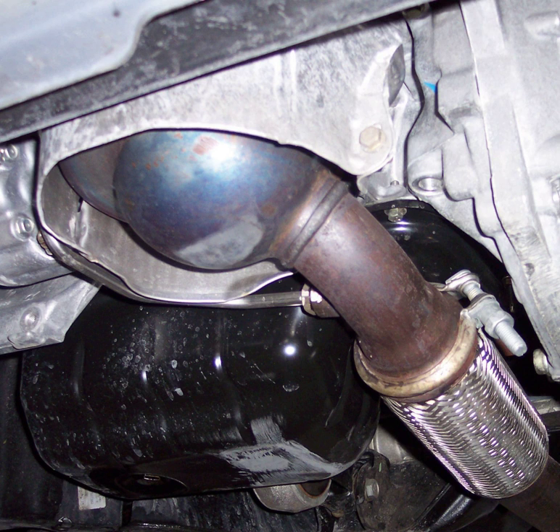The most common filter is made of cordierite, a ceramic material that is also used as catalytic converter supports. Cordierite filters provide excellent filtration efficiency, are relatively inexpensive, and have thermal properties that make packaging and installation in the vehicle simple. The major drawback is that cordierite has a relatively low melting point, and cordierite substrates have been known to melt during filter regeneration.